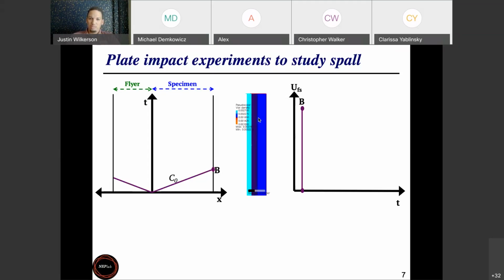It's not shown here in the visualization, but the stress state and the strain state are actually fairly simple as well, at least for isotropic material. For an isotropic material, the strain state is uniaxial strain. That means as the shockwave propagates through, the material is being squeezed in the longitudinal direction, the direction that the shockwave moves, and then there is no Poisson's contraction in the lateral directions at all. Those stay fixed. As a result of that, a multi-axial stress state is developed. There's stress in the longitudinal direction, and there are stresses in the lateral directions as well, because it's basically like a confinement. We don't allow the Poisson's contraction due to the timescales of the shock propagation. And so that's the stress state that you end up with.